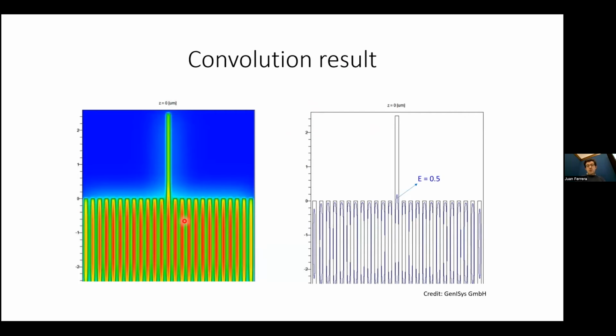as well as the corners. So if you normalize the energy that you're depositing as 1, then let's say that you have arranged your resist process so that it will clear at a dose of 0.5. In that case, the pattern that you would get after developing is given by these blue contours. So you would see that the single line has disappeared, and the corners and the edges also have suffered from the proximity effect.